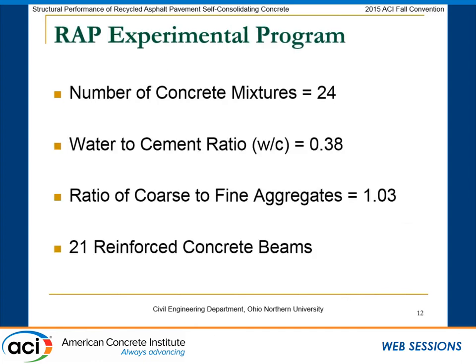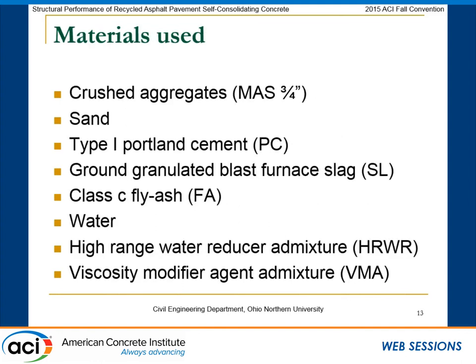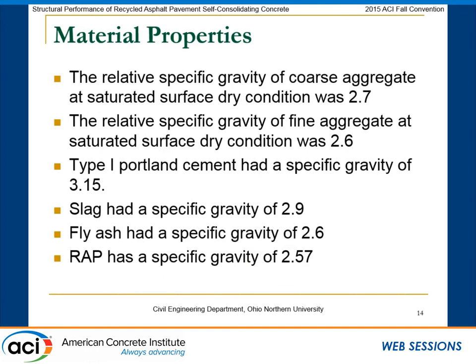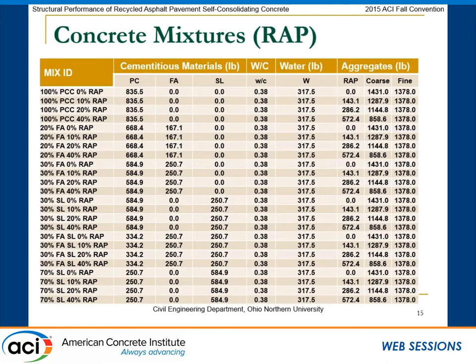We developed 24 concrete mixtures with a fixed water cement ratio of 0.38, and the ratio between coarse to fine aggregates was 1.03, and also we cast 21 small reinforced concrete beams to assess the structural performance of these new self-consolidated concrete with RAP. So these are all of the materials that have been used in creating the self-consolidated concrete mixture. So here we use the fly ash, slag, and we use the high-range water reducer and VMA. And these are some specific gravity values for all of these materials here.